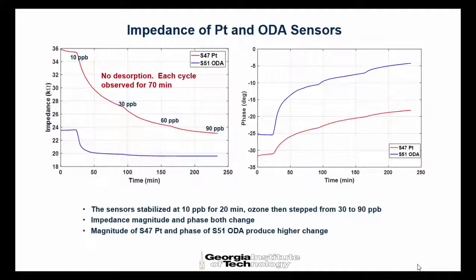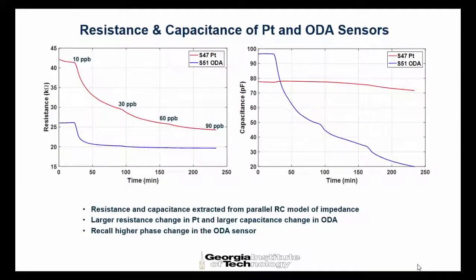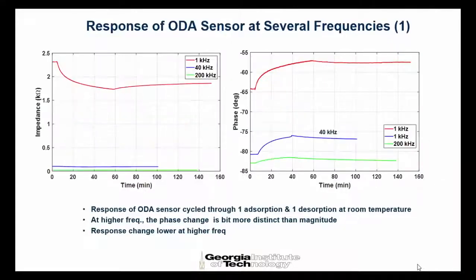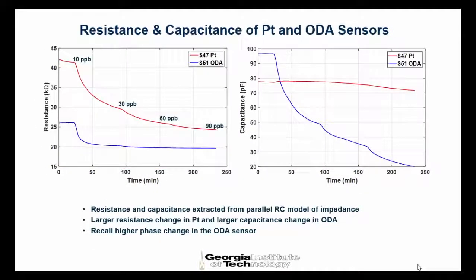So you have 2 degrees of freedom that you can control by making an array of these 2 sensors. One gives you good magnitude response, the other one gives you good phase response. So any cross sensitivity to different gases or humidity can be well controlled by combining sensors and then doing data processing later. This theme is being circulated by many authors in this conference. So it's an emerging research trend to use multiple sensors and do some processing.